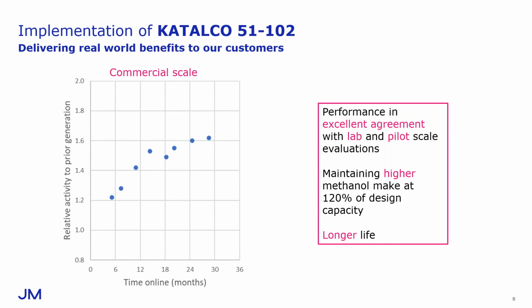And this figure shows the performance of the first commercial charge of 51-102 installed, which has now been online for over 2 years. Here, the activity of 51-102 is plotted relative to that of the previous charge of catalyst that was installed at the same facility. And that previous charge was, again, Johnson Matthey material. It was the best of our prior generation catalysts.